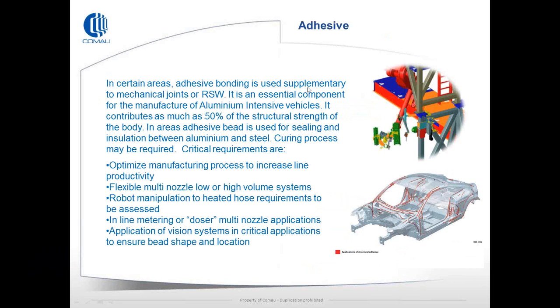Again, adhesives. In certain areas, adhesive bonding is used as a supplementary to the mechanical joints, or resistance spot welding. It is an absolute essential component in the manufacture of aluminium-intensive vehicles, and it can contribute approximately 50% of the structure strength of the body in terms of its overall performance. In areas where the adhesive bead is used for sealing, as well as insulation between aluminium and steel, so as to prevent any corrosion. The curing process may also be required.